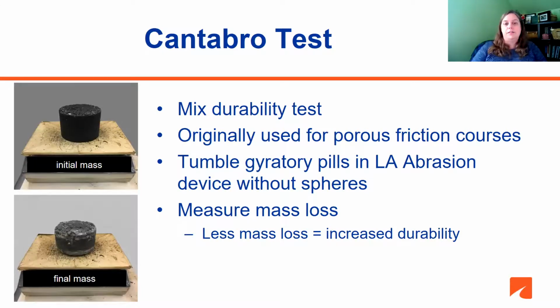The Cantabro test is our mixture durability test. This test was originally used for porous friction courses. In order to perform the test, you will take a volumetric gyratory pill, determine the initial mass, tumble the pill in the LA abrasion device without the steel spheres, and then measure the final mass afterwards. Less mass loss will result in increased durability of mixes.